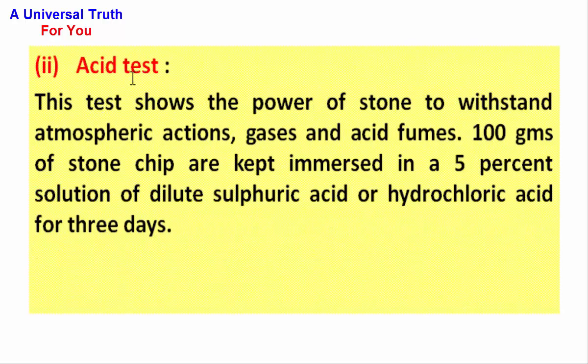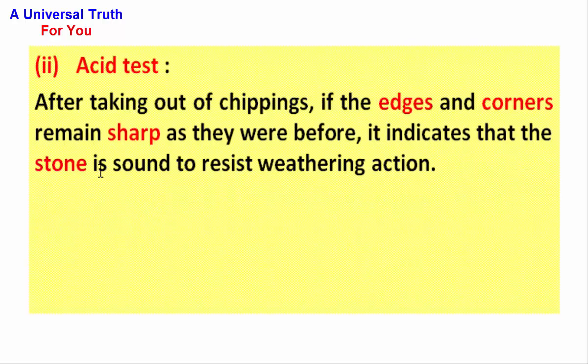Acid test: this test shows the power of stone to withstand atmospheric actions, gases, and acid fumes. 100 grams of stone chips are kept immersed in a 5% solution of dilute sulfuric acid or hydrochloric acid for three days. After taking out the chippings, if the edges and corners remain sharp as they were before, it indicates that the stone is sound to resist weathering action.